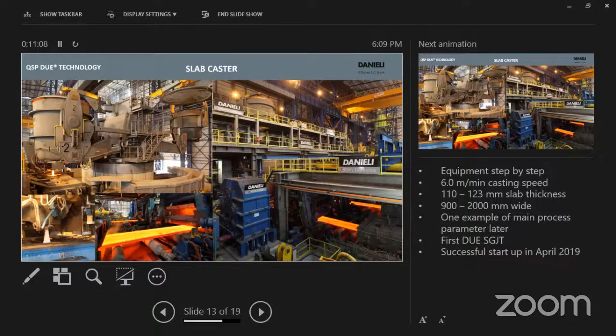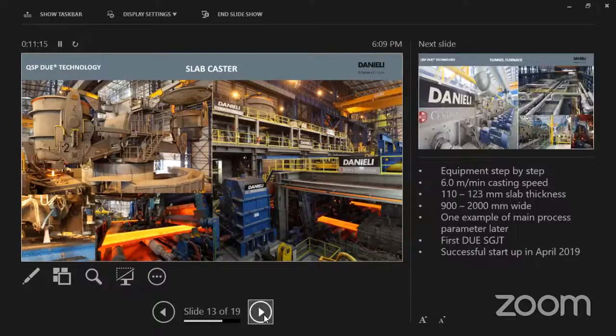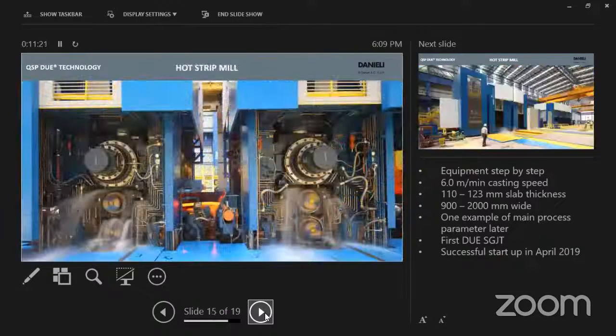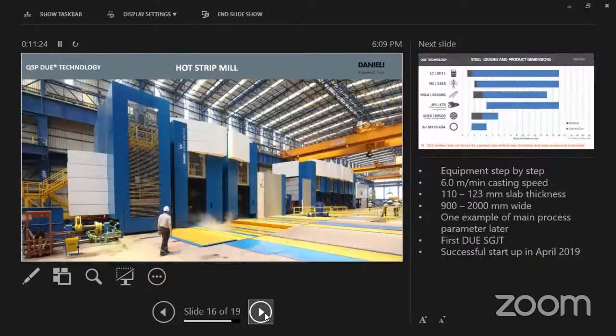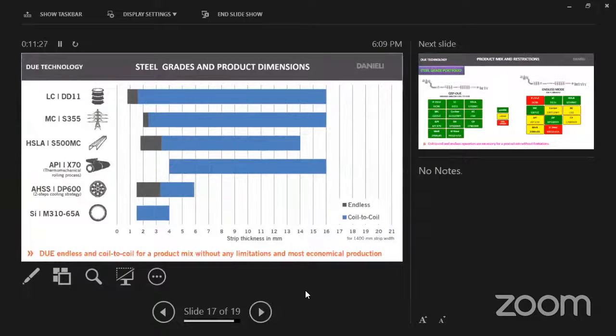So these are some pictorial photographs of the casting position. This is a pendulum shear, you can see. Tunnel furnace, mill. Now there is an interesting slide which I am telling you. I told you earlier about which mode you should put the coil in. The blue color shows that your production should be in coil to coil, because you are going from 1.5 millimeter thickness to higher thickness. So that is the reason you have to go for coil to coil.